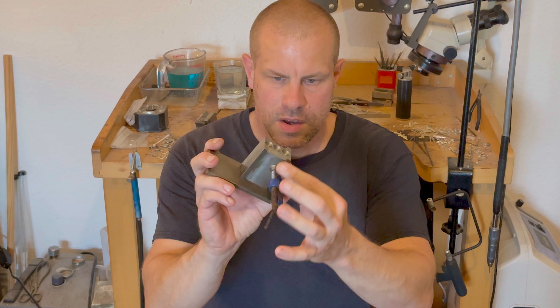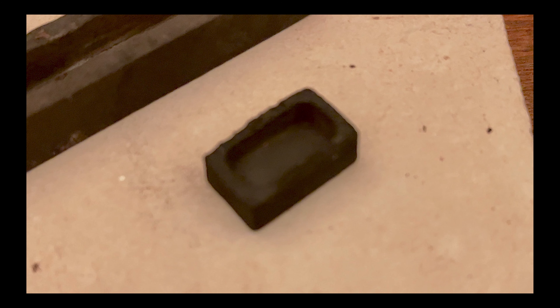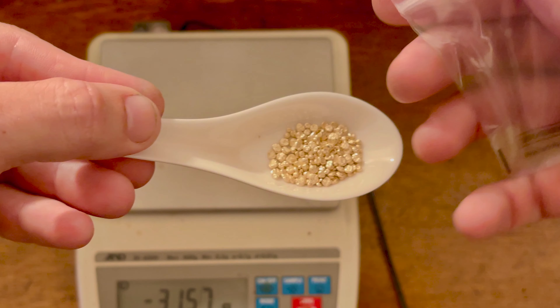The pros of graphite for small melts are better detailing, allowing for more detailed and intricate designs; uniform cooling, which promotes a more uniform ingot preventing defects like hot tears; and ease of use, as graphite moulds are easier to handle and set up. The cons are cost — they can be slightly more expensive initially but prove more cost-effective in the long term due to their durability — and the fact that they degrade a little with each use and require careful handling to prevent wear and tear.